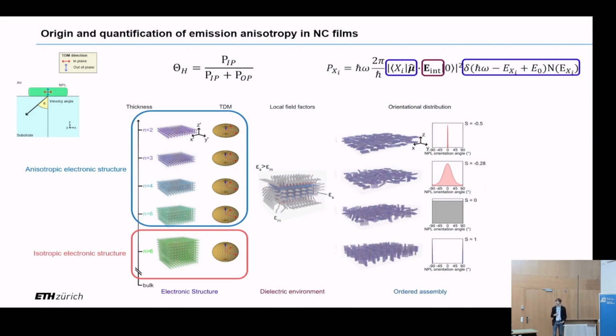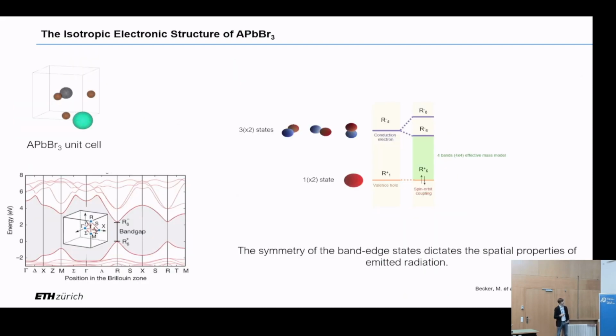We will start tackling the problem for weakly confined nanocrystals, which is a simpler problem because these are nanocrystals where the electronic structure does not change with respect to bulk, or not significantly. So we can disregard this effect and focus on the dielectric environment. This is briefly why lead halide perovskite is an isotropic emitter. This is briefly representing the band states, and isotropy comes from the conduction band. The conduction band is actually six states, but you can think of them as three states which have p-like symmetry, like the p orbitals. So they effectively behave as three orthogonally oriented dipoles, thereby leading to isotropic emission.